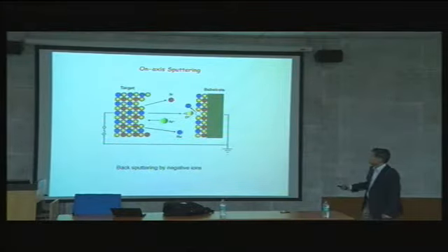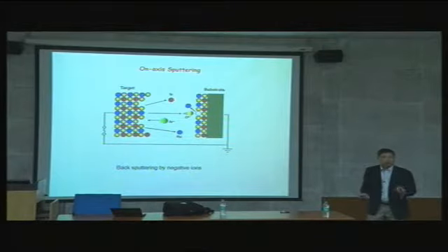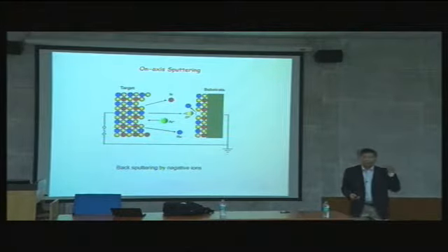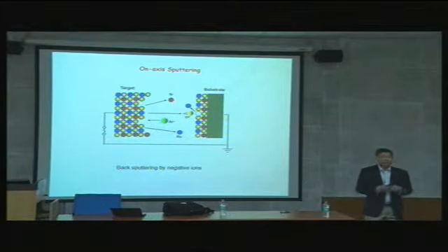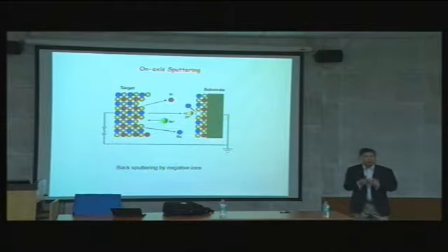So the way sputtering works is either RF or DC. You need DC for conductive material, and RF for insulating material. But basically you can sputter any material, any melting temperature. Tungsten, even you can sputter. Sapphire, you can sputter. Any materials, no issue of temperature. Okay, so that is the beauty of this sputtering.